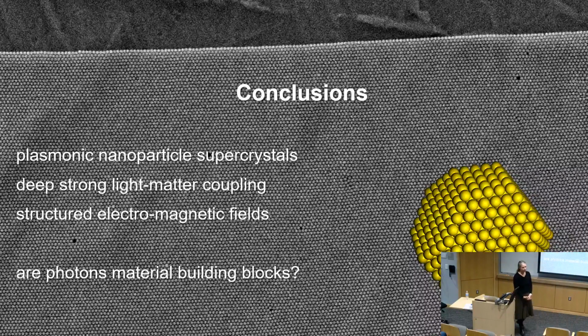I mean, the polystyrene was mainly used in order to stabilize gold nanoparticles, because the typical CTAB and so on that you use normally to stabilize gold nanoparticles don't work if you go to larger ones. Yeah, the key part is the coating uniformity, right? In order to form a supercrystal, you need the coating to be uniform to form this structure. If you have a relaxed coating, with longer brush and shorter brush, that can be really hard to form a superlattice structure.